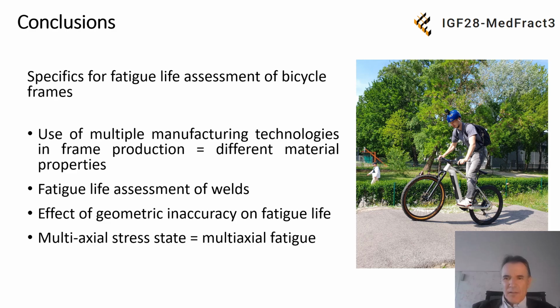At the end, it is possible to conclude with this summary of the specifics of fatigue lifetime assessment in bicycle frames. First, there are multiple manufacturing technologies present in the frame production, and these different manufacturing technologies lead to different cyclic material properties. This is a fact, and it is necessary to consider it. The second specific is the welds. Not welds in general, but the specific kind of welds present on bicycle frames due to the change of thickness around the cross section. The welding parameters are very complicated to adjust appropriately, and then these welds lead to a lower S-N curve than we expect in weld joining.